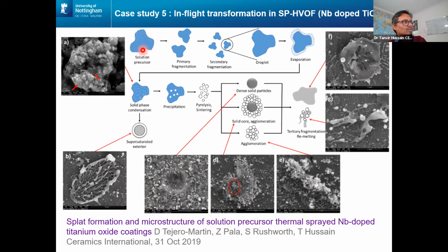So this is a solution precursor droplet in a flame. It goes through primary and secondary fragmentation. We have got a droplet. The droplet evaporates on the surface. We can see solid phase condensation, then precipitation, and then depending on the condition, it can turn into a dense solid particle, could turn into a particle with a solid core, or agglomerated particles.